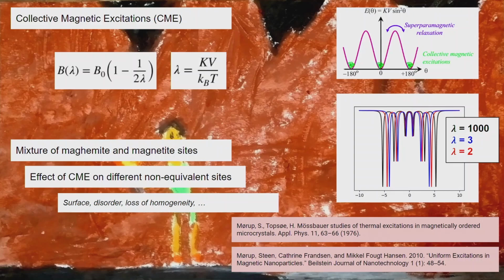So what you will see if you have something very big: lambda is KV over kBT, so lambda is proportional to volume. I will say lambda a lot of times here. When you have high lambdas, you have the bulk spectra, but if you reduce the volume, you will start to have the same spectra, but shifted because of the reduced hyperfine field. So in our sample, we have a mixture of maghemite and magnetite. So we have sites for iron in maghemite, both sites, and also for magnetite, both two sites.